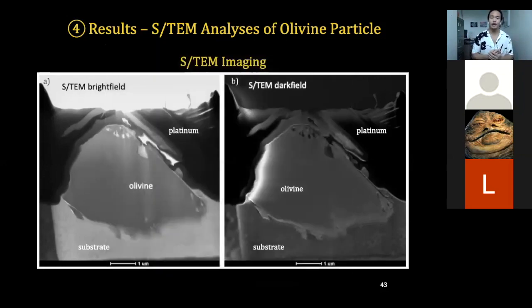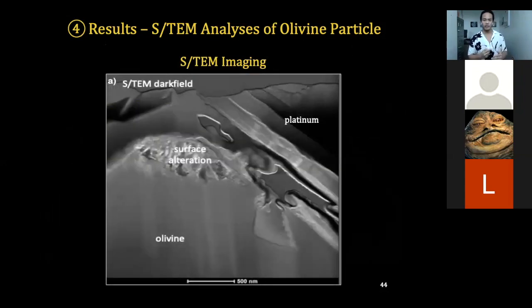Looking back at our samples, you can see that we don't see any of those solar flare tracks, indicating that we probably have not spent a significant time in space to get them. What we do see, however, are some features near the surface that are alteration or just surface material. Looking at that a little bit closer, you can see that the labeled surface alteration has a morphology that is different from the actual particle. There's also some material present that I'm going to circle with my mouse right here, which is likely the material that was on top of our particle before we created the thin section.